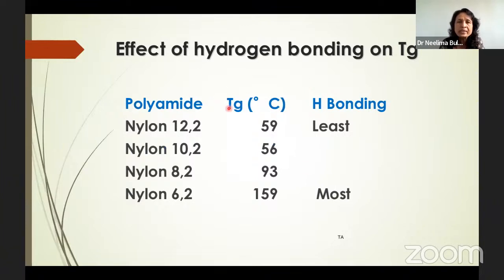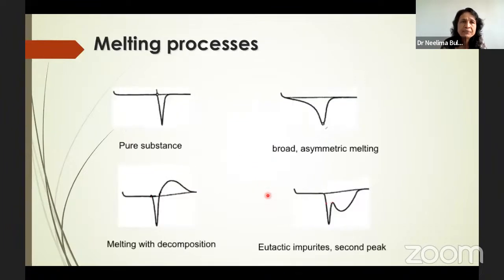So hydrogen bonding. If you increase the hydrogen bonding, TG increases from 59 to 159 degrees centigrade. Now, from the melting curve also, you can find out the purity of your sample. Because see, for the same sample, if you are getting a sharp melting, your material is pure. And if you are getting this type of broad, asymmetric melting, for the same material, then you can say that there is a difference in the molecular weight of my sample